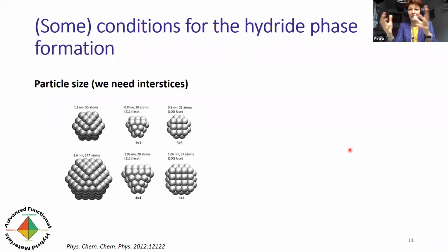And I'm sure that you're familiar with the idea of increased surface to volume ratio as we make particles smaller and smaller. But just to show you an example, here we have a 0.8 nanometer sized metal cluster, and it has 18 atoms, which means that there is only one atom in the middle and 17 atoms are on the surface. So that means that in a practical sense, there are no interstices in this particle, because it's simply too small for those interatomic spaces to be around for the hydrogen to occupy.